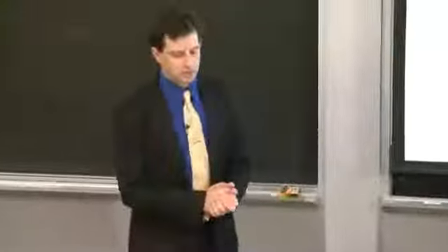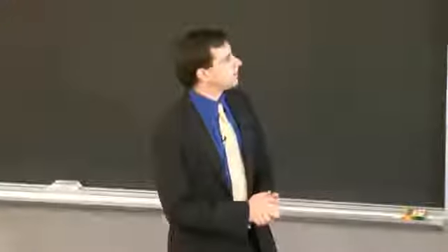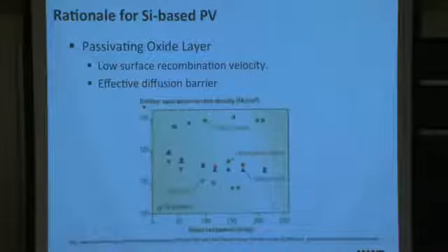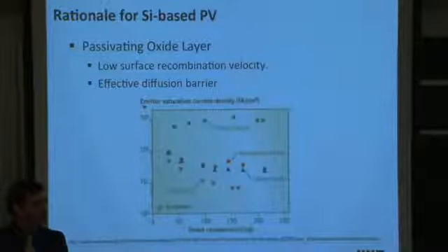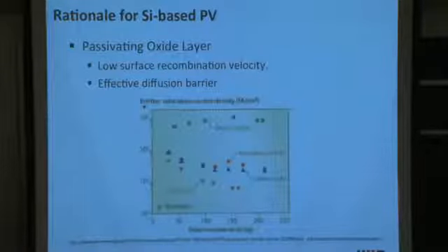But from a technological point of view, why did silicon evolve to the point where it is today? It forms a very tenacious surface oxide. So if you were to expose a piece of pure silicon to air, the surface oxide that forms is very, very strong and very resistant and very dense. So unlike some materials that corrode when exposed to atmosphere, silicon oxidizes maybe the first few tens of angstroms, hundreds of angstroms, and then it peters out. So it's a diffusion-limited oxide growth mechanism that eventually stabilizes at a very thin but very dense and very protective oxide layer. And so the risk of having a silicon wafer degrade inside of a solar module is very low.